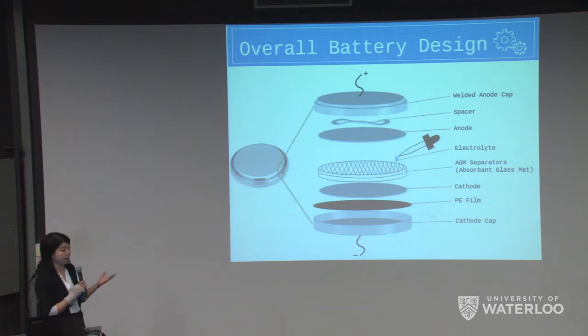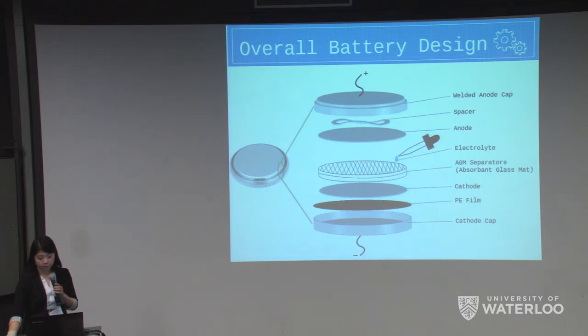So the fabrication began with starting with a cathode cap, and then we moved on to placing a polyethylene film on top of that. And then following that, we were placing a lithium manganese oxide cathode. And in order for the battery to have an acceptable capacity, the active material, which in our case is lithium manganese, is a thick layer of porous particulate paste.